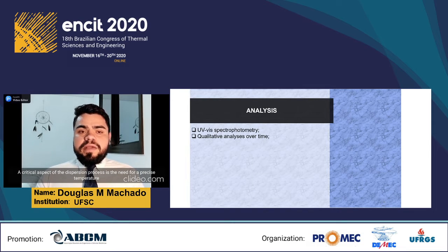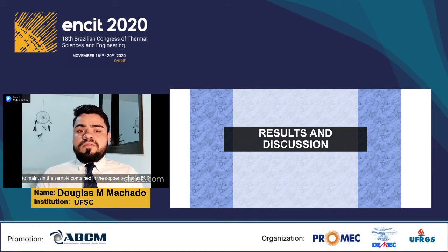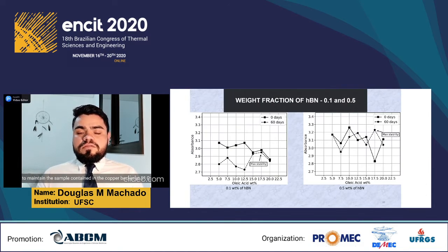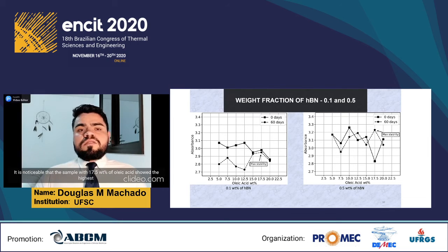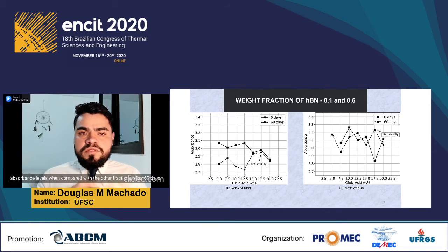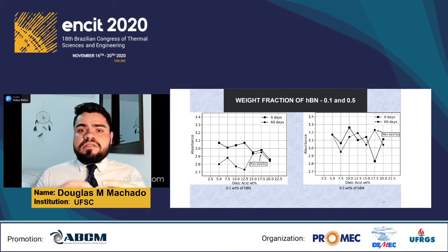A critical aspect of the dispersion process is the need for precise temperature control of the samples, which was ensured by using an ultra-thermostatic bath to maintain the sample contained in the copper beaker at 5 degrees Celsius. It is noticeable that the sample with 17.5% of oleic acid showed the highest absorbance levels when compared with the other fractions after 60 days.